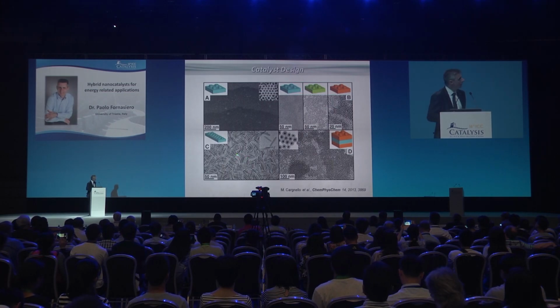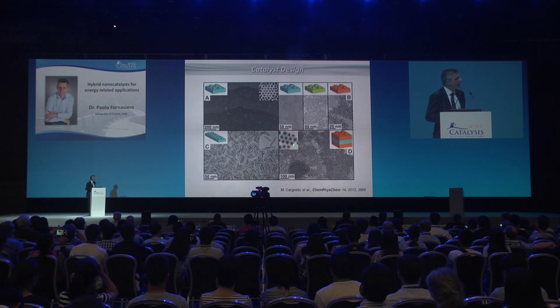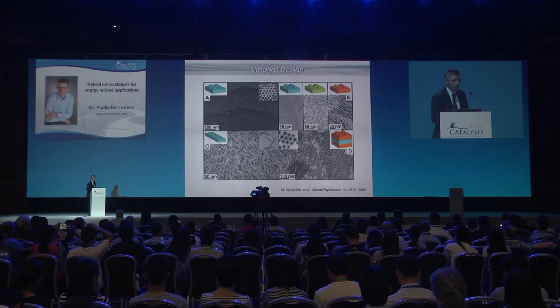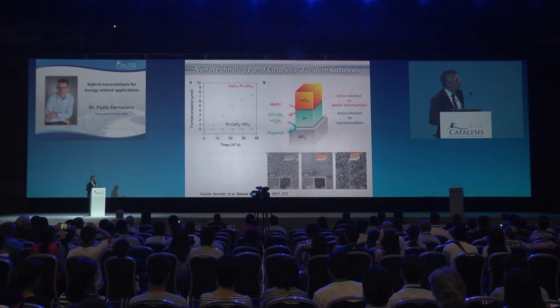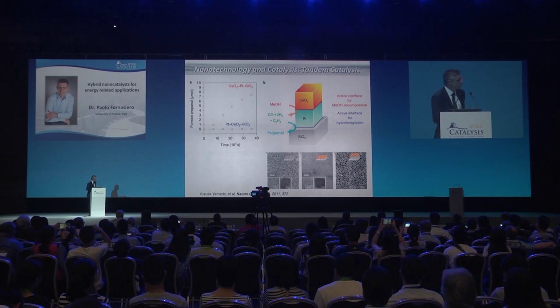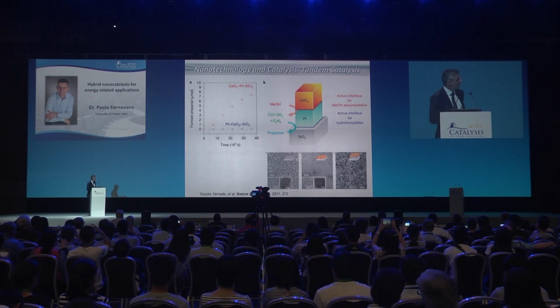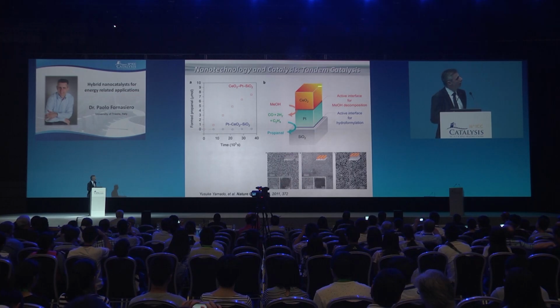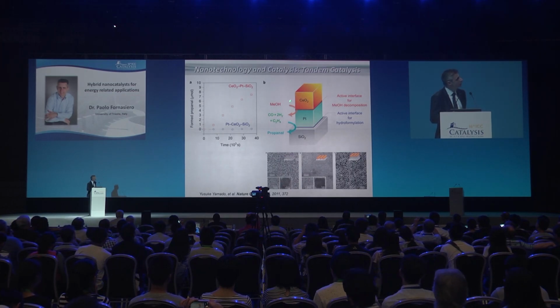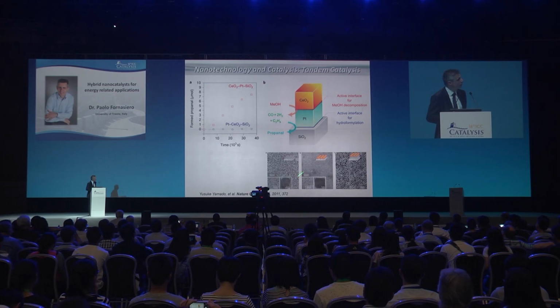You can have long bricks, spheres, or you can also combine in core-shell type material and so on. You can have polyhedra, you can have cubes, and so on and so forth. Just from the literature, I will show you a nice example from Gabor Somorjai's work in which they prepared ceria cubes connected to platinum cubes on a silica substrate. This is the cartoon, and these are real TEM images.